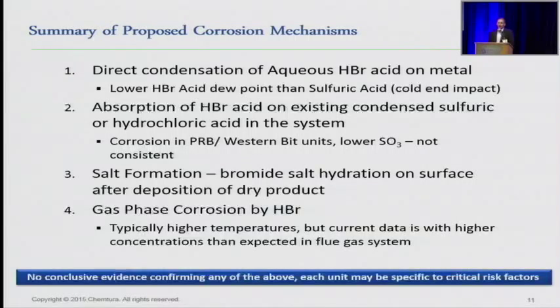The proposed corrosion mechanisms here, again, nothing really hardcore identified, but you have all these things. You can have the condensation because of dew point of the acids. You could get absorption of that HBr in sulfuric acid. They're fairly soluble. You can get salt formation where you have a cycle of temperature going up and going down, where you're getting salt deposition and then condensation, and now that salt on the surface acts as a corroding agent. Or you could have gas phase corrosion. Again, you wouldn't necessarily expect it at these conditions, but it is one that is possible.